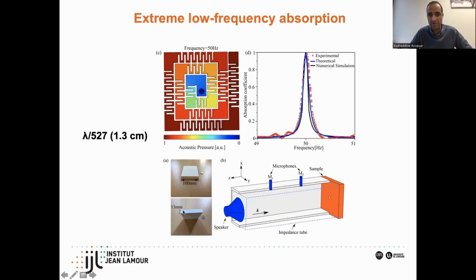So that's what we did. Here you have an absorber of 13 millimeters working at an extremely low frequency of 50 hertz, which is actually the lowest frequency that exists right now. We did lower than that, but it's one of the lowest acoustic absorbers in terms of frequency we have realized. The problem of absorption at low frequencies is that the resonance is extremely sharp, which means you usually have a very narrow band. That's problematic because usually you need to realize a broadband feature, which is extremely difficult.